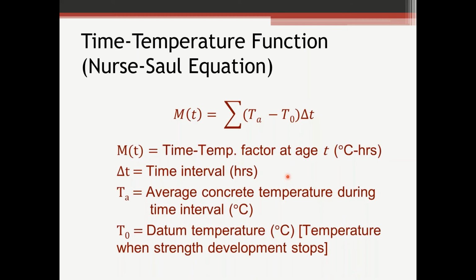Some people use 0 for datum temperature. The ASTM gives a little bit of guidance in the appendix on what to use, but 0, 1, or 2 degrees Celsius is pretty typical for a datum temperature. So you can see it's just a summation of all of the times and temperatures together. So there's your product of time and temperature. It's kind of the area under the curve.